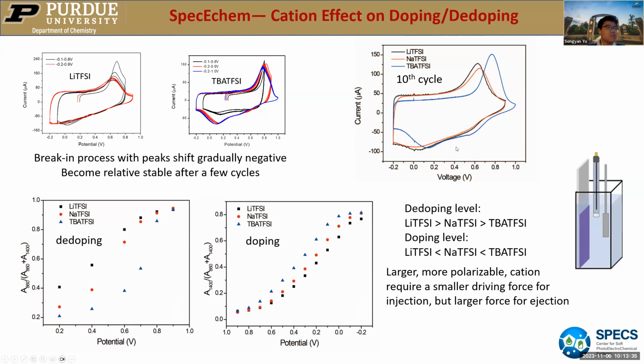When we compare these CVs, for TBA TFSI, it has the highest oxidation potential and the lowest reduction potential, and then sodium and then lithium. When we compare their de-doping and doping levels, I compare them separately. For lithium TFSI, it has the highest de-doping level at the same potential, and TBA TFSI has the lowest one. But in the doping process, it's reversed. It has a reverse sequence.